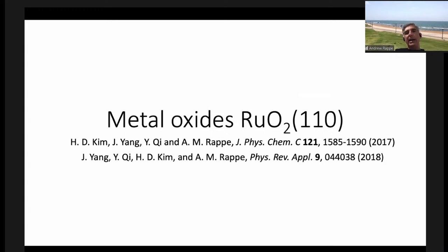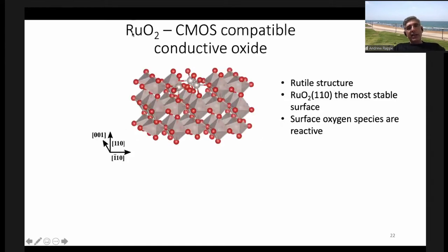Okay, so my colleagues thought, what about a conductive oxide? And ruthenium oxide is a famous one. So we decided to do the same chemical reaction in the computer using our first principles density functional theory calculations and look at it side by side with the platinum to see if it's better or worse. So ruthenium dioxide is CMOS compatible and it's a conductive oxide.